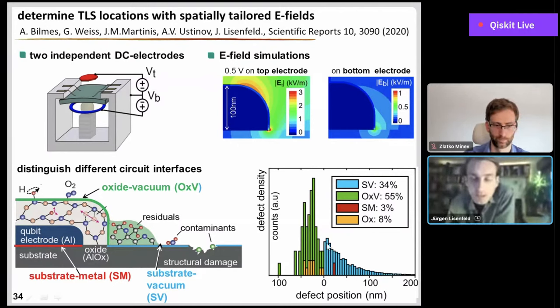And I guess, again, you can of course understand that this is a useful measurement. It can really help you nicely to debug your fabrication. In this case, probably we should have cleaned the photoresist away better to maybe reduce these numbers of defects on the substrate-vacuum interface. But in general, I would say this is a very nice tool to learn where your defects actually come from and what you should do to get rid of them.